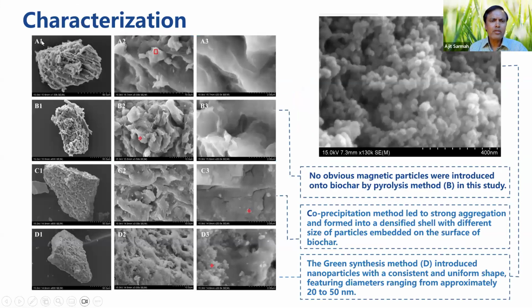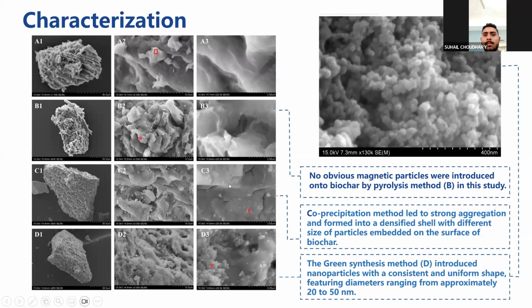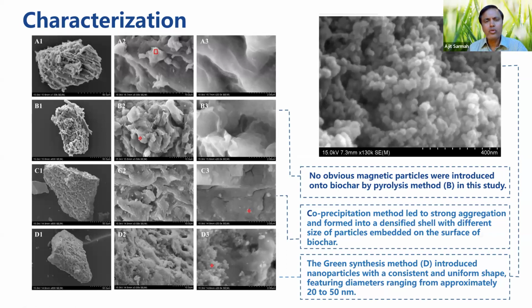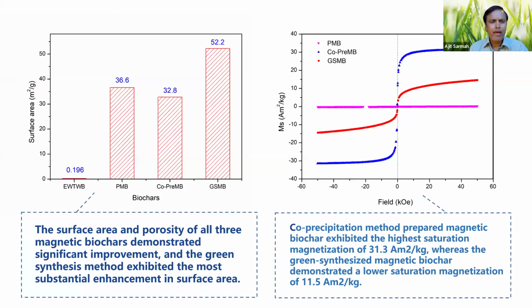This is again the scanning electron micrograph characterization, where you can see what's actually happening inside the biochar. Here, what you can see is that there were no obvious magnetic particles introduced. The co-precipitation method led to very strong aggregation. This was a study recently done, and this is quite unique. We are now trying to find out if it is possible to scale up.